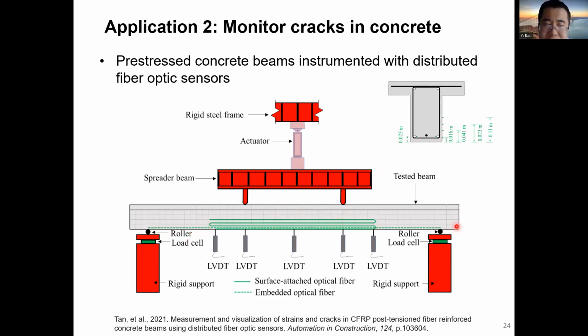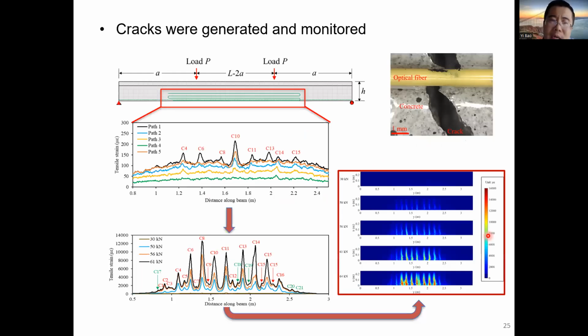So we applied four-point bending to this beam, and when the load increased, at the very beginning, we measured the strain change, and then as the load was increased, we were able to detect some peaks from the fiber optic sensor, and each of the peaks represents a crack in concrete. When the applied load increased from 30 kilonewton to 61 kilonewton, as you can see, more peaks were generated, and for existing peaks, the magnitude increased with the increase of load. So this means the distributed sensor was able to monitor the initiation and the growth of cracks.